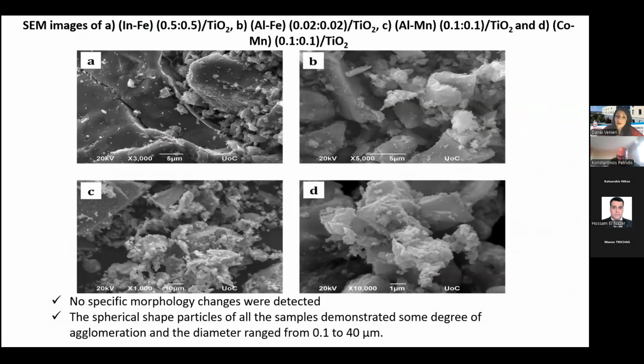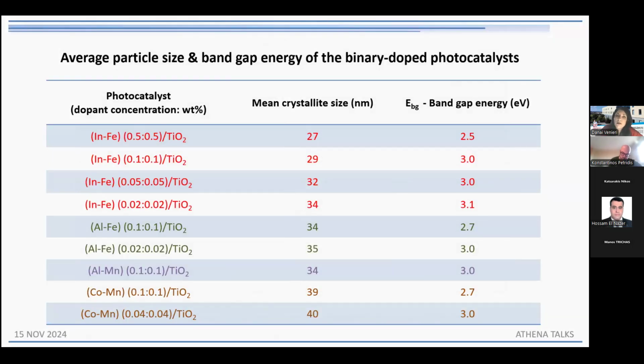Here are the SEM images. Upon doping, we did not detect any specific changes in the morphology. And here you can see even more characteristics regarding the average particle size. I should mention here that the average particle size plays an important role, up to a certain extent, regarding the effectiveness and the inactivation of microorganisms. And of course, the band gap energy here. Anything less than the 3.2 I showed you before, which is the band gap energy of titanium dioxide, seems to be a good choice. But, okay, yes, we did achieve those results, that characterization that you may see. I'm not going to delay you with this.